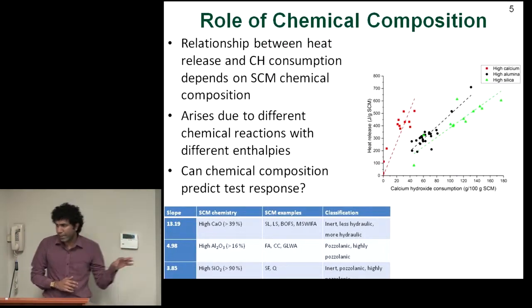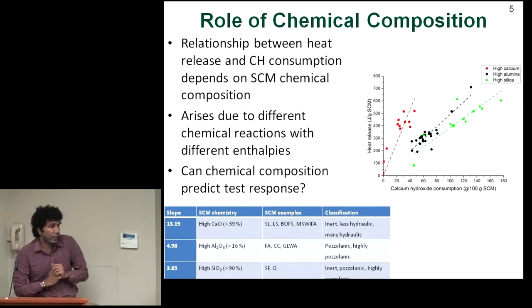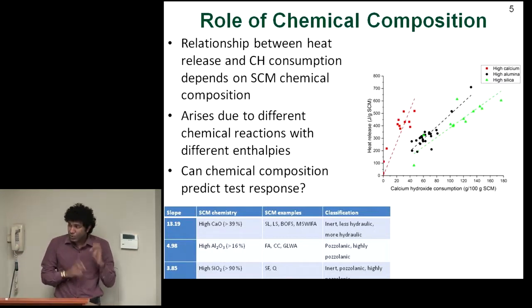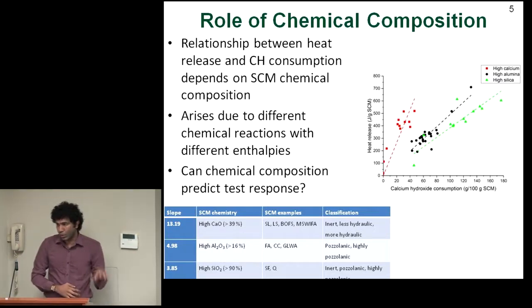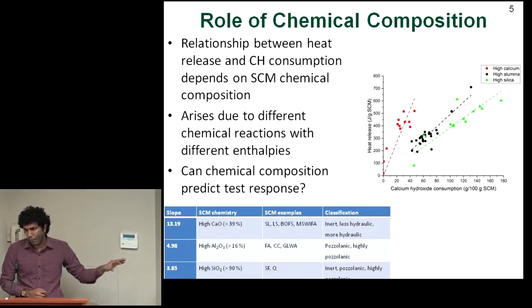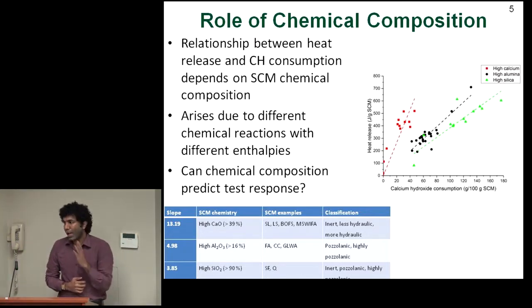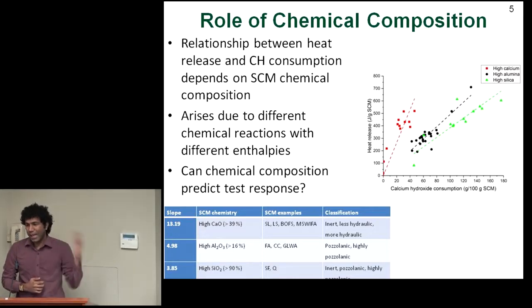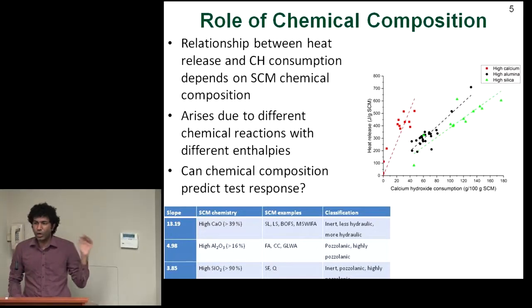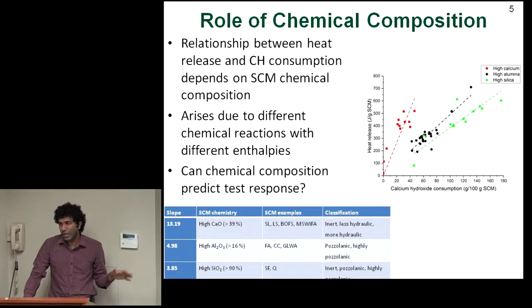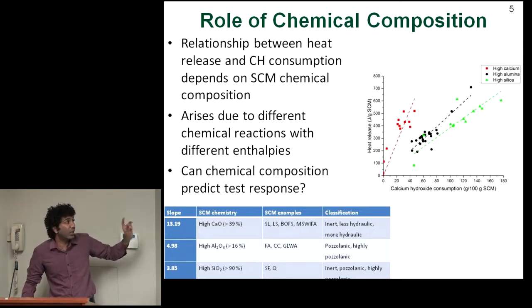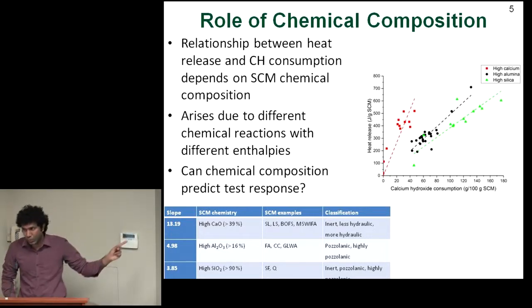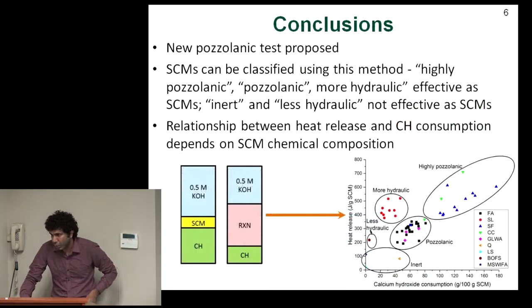So we took all of those 50 materials, grouped them into 3 different types depending on their chemical composition, and this is just the bulk chemical composition. Depending on their calcium, alumina, or silica content, you get very different slopes, and this seems to arise because of different reaction enthalpies. And this is really nice because then we only need to measure one of these 2 tests to get the other one. So the idea is we can predict fundamentally from the chemical composition the response.